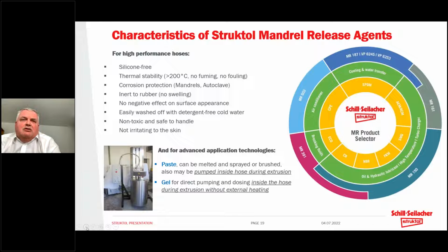Next slide, please. So yeah, on the market there are a number of mandrel release agents for shaped hoses. These products are considered to be silicone free. Silicone is absolutely not required on the inside of automotive hoses. High degree of thermal stability. We don't want the release agents to cause mold fouling on the surface of the mandrel. Certain corrosion protection systems may be built in to protect both the mandrel and the autoclave from the degradation that might occur.